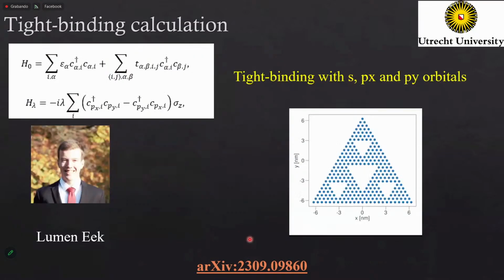To understand this, and to use a bit more of the parameters of the material, we also use a tight binding model. This was done by Lumen, a PhD student from Christian's group. He used a tight binding model, adding s, px, and py orbitals that are relevant for bismuth, or at least something close to bismuth, close to the Fermi level.